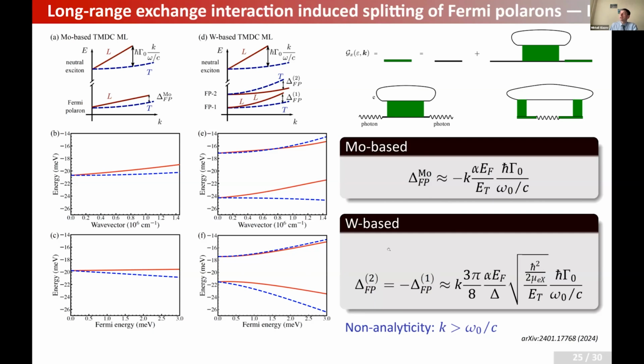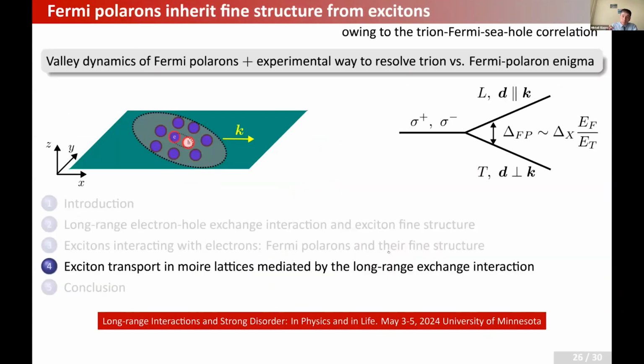But anyway, the correlation between the trion and the hole in the Fermi sea brings about this many-body complex, the Fermi polaron complex, and makes it possible for the trion to have this longitudinal-transverse splitting, which is inherited from the exciton, so it contains the factor like Fermi energy divided by some characteristic trion energy, the binding energy, or the splitting of the trion states. And it may also be important for studies of the Weyl physics of trions and Fermi polarons.